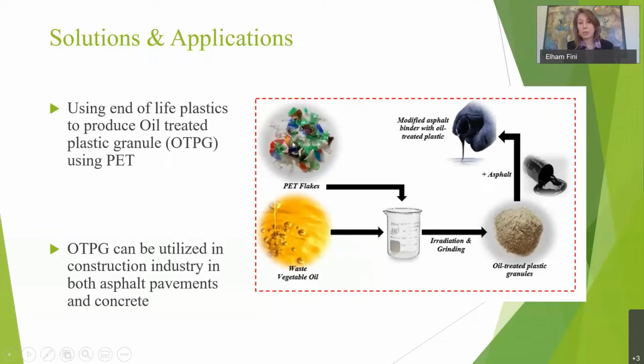The mixed plastic is treated on the surface with an oil to make it compatible with the rest of the building material. So in this scenario, we treat it with this waste vegetable oil in this bottle, and then we apply a bit of radiation. At that point, we grind it and we get these granules that you can see here. From this product up on the left, we get this one on the bottom right. And this product can be directly added to construction of the concrete or asphalt roads.